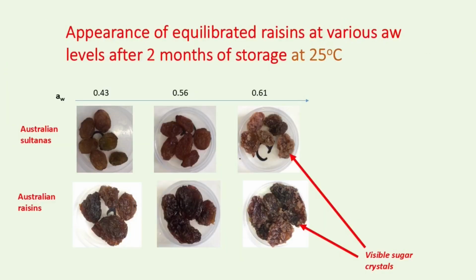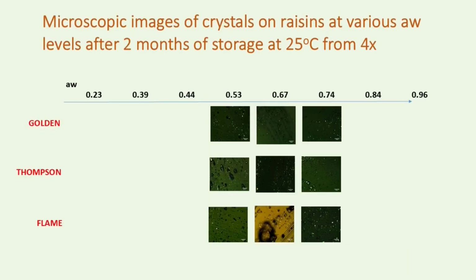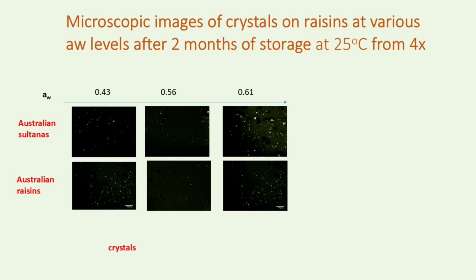Then we tried to store the sample for an even longer time, 2 months, at different temperatures, including 25 degrees Celsius. You observe visible sugar crystals on the surface. And then we also observed microscopically, like the Maltese cross. You can see the very bright light of the crystals, just using a simple microscope in different varieties. And you can see that using different humidity it was evident. And then this is about honey. A similar process happens to honey.